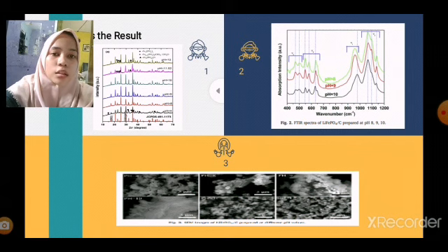It can be seen that only the absorption band in the range 950 until 1,000 cm minus 1 undergoes a shift along with the pH value, and the asymmetric stretching V3 mode, V2 mode, and V4 mode remain almost unchanged in position.